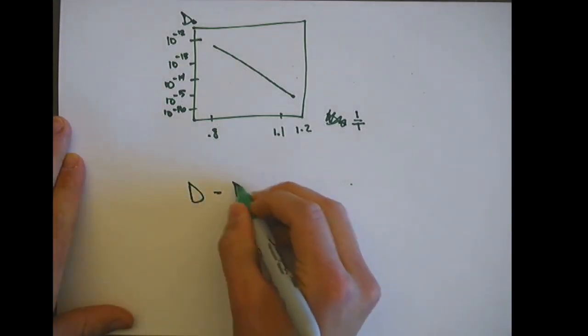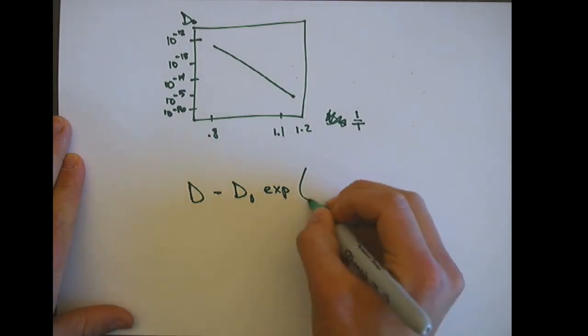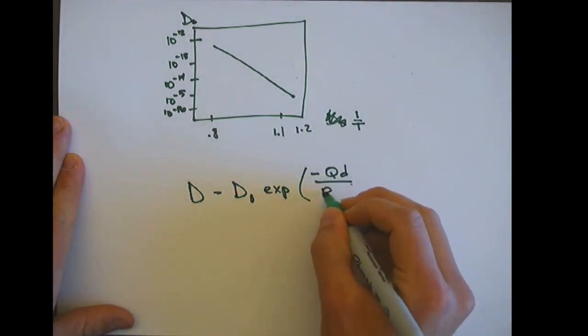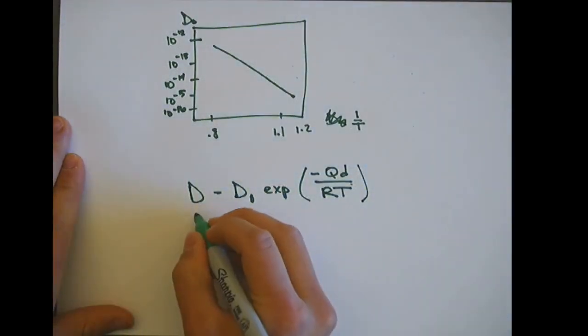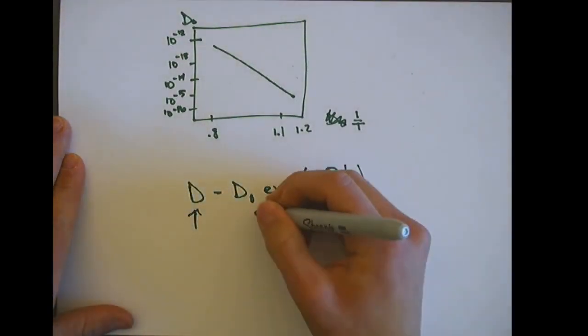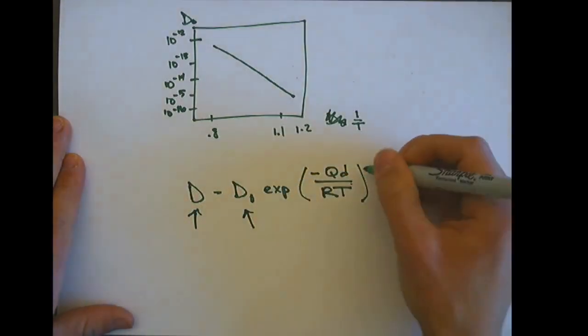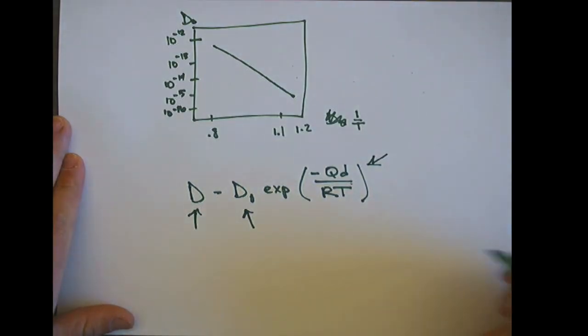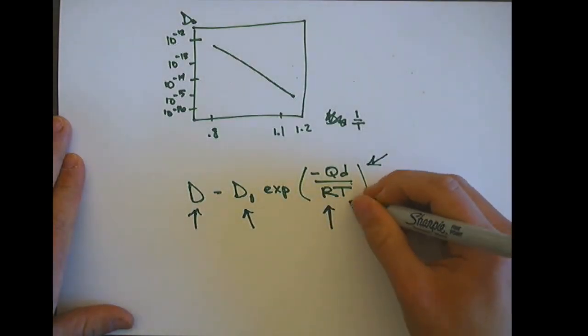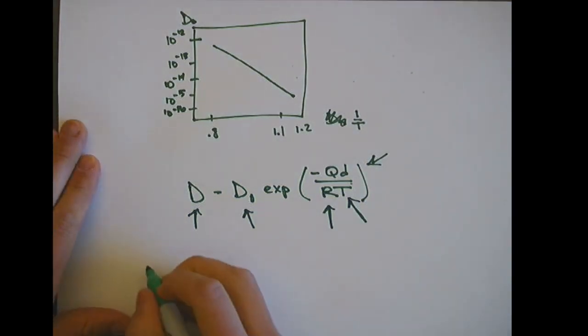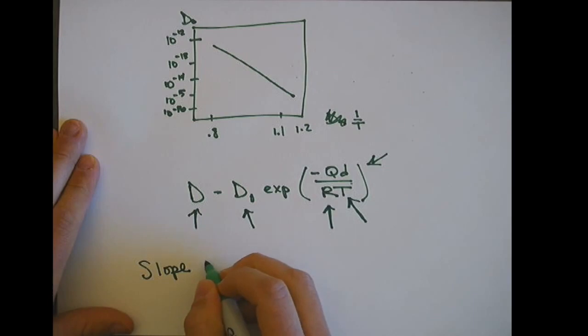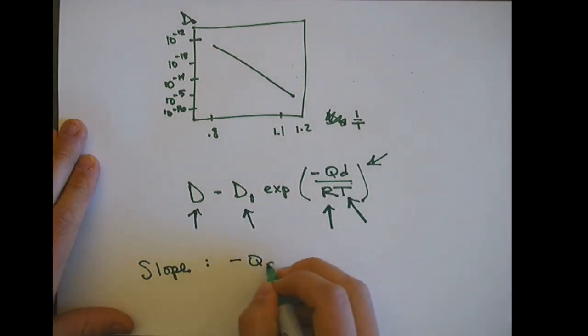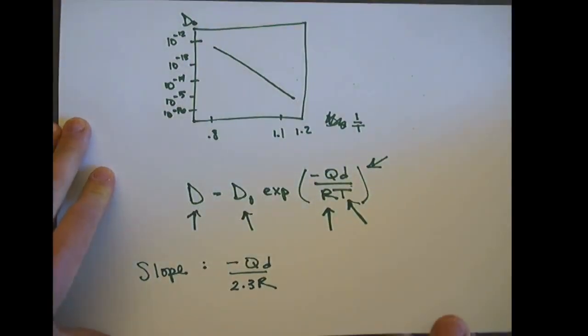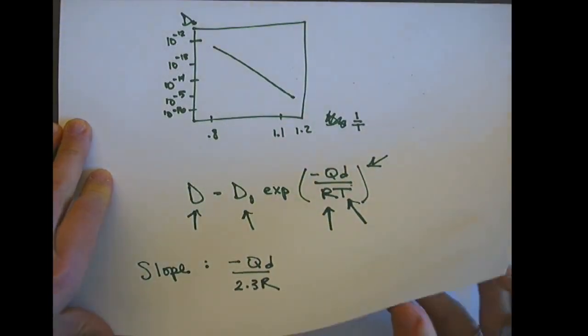Okay, so the equation given is D equals D0, which is our pre-exponential, times e to the negative QD over RT. So D is the value for the diffusion that we're going to get. D0 is our pre-exponential. QD is the activation energy that we talked about before, and then R, our constant R that we're familiar with, and T is the temperature, again in Kelvin. So the slope of this line, we want to try to make it linear. We know that's going to be QD over 2.3 R. Now the reason that it's 2.3 R is that it's a logarithmic function. If it was a natural log, it would just be R actually.